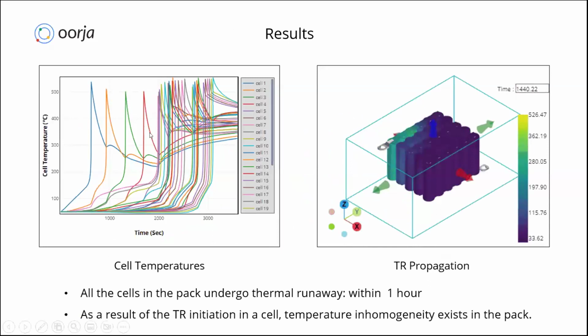So here in this case, with this study, you can see that all the cells go into thermal runaway because there isn't any cooling mechanism provided. It also doesn't have any spacing. It doesn't have any casing available, so there isn't even a basic heat sink available in order to take out the heat from the pack. And hence, you get to see that slowly all the cells start going into thermal runaway and the entire pack also undergoes thermal runaway within 1 hour itself.